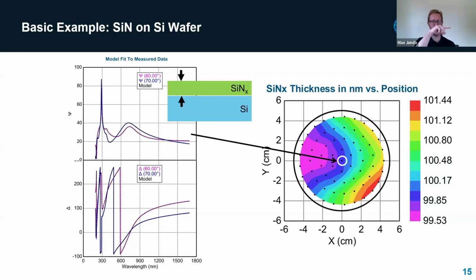If we measure in multiple spots all over this entire wafer, we can do this fitting at each of those spots, and then we get a map of what the film thickness is over the entire wafer. So this is a really good case. Not a lot of limitations here. Works really well. That would be considered a bread and butter case of ellipsometry. So let's go to the next slide, Lyle.